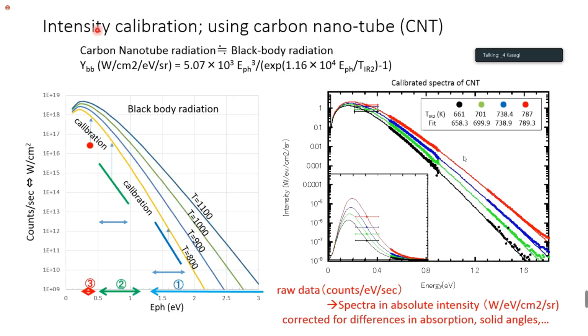Okay, how do we calibrate those respective measurements? We use carbon nanotubes. This is a very nice material because the radiation from carbon nanotubes is known to be just black body radiation. We can calculate the black body radiation using this formula and plot this. For example, at 800 K, your output from a thermometer is this. You just normalize this, and for this region you can normalize that too. Then we can get a calibrated spectrum. So this is the result of the calibrated spectrum of carbon nanotubes. Black and green and blue and red are the different temperatures.